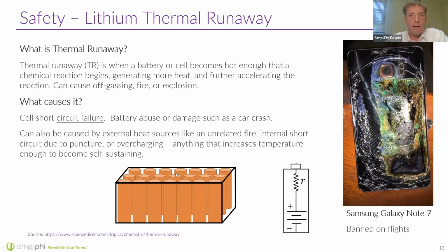a car crash. So imagine that the center cell gets really hot and starts off-gassing. That's a flammable gas that's coming off. And if you have an ignition source, like a spark, or even if the cell just gets too hot, it can start burning. If one cell does that, it starts to heat the other cells up around it. The other cells around it can then start off-gassing, and you have a runaway fire. And that's the challenge with lithium-ion batteries. Again, LFP batteries are the most likely to not experience this runaway. They're the safest chemistry.